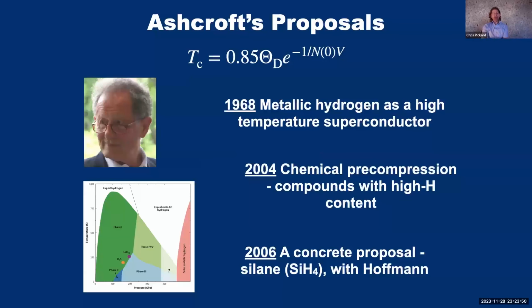Now, I'm just going to turn back to Neil Ashcroft's suggestion that hydrogen mixed with other elements might become high-temperature superconductors, because this has actually spawned a whole very active field of research whose conclusion has not yet been fully worked to the end. So what Neil Ashcroft proposed in the early days, in the 60s, was that potentially metallic hydrogen might be a high-temperature superconductor. And that was based on a simple model of superconductivity, which related the superconducting transition temperature to the Debye temperature, and then some electron-phonon coupling terms and density of states terms of the electronic structure in an exponential.